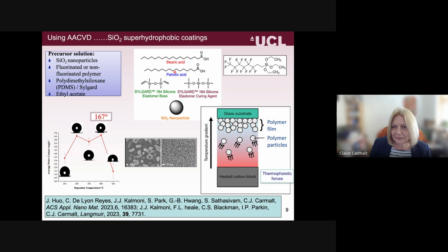But for the AACVD, one of the problems you get is that when you try and deposit a super hydrophobic coating or a hydrophobic, it's not very adherent to the glass substrate. And what often happens is, I mentioned about the AACVD that you have your glass substrate at the bottom and your top plate. So normally your film grows on the glass substrate. But what happens when you're using large polymers or large particles, that you get thermophoretic forces, and this ends up causing the super hydrophobic film to deposit on the top plate rather than on the bottom, which doesn't really matter apart from it's the wrong way up, and you would have to think about things if we were incorporating it into the industrial process.